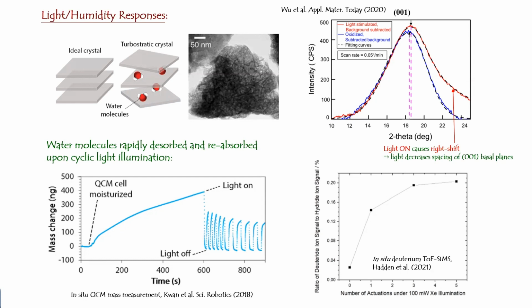So therefore, the material would respond to photothermal stimuli if water molecules are driven out. Okay, so if water molecules are driven out, the material will shrink. So how to prove that? One experiment that we have done is to put a light source inside the XRD, X-ray diffractometer. So every time we switch on the light source, to go from the blue to the red, there is a right shift of the peak corresponding to this basal plane of the HCP crystal structure. Right shift means a reduction in lattice spacing. So that proves the fact that the lattice spacing is reducing.